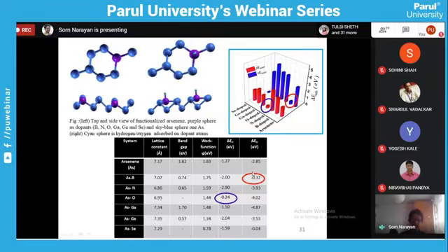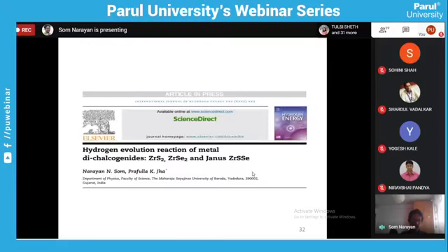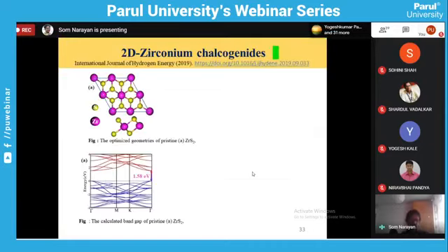And we now go to another system, that is zirconium Janus, ZrS2 or ZrSe2. We know that ZrSe2 is used as a photocatalyst in bulk also, but in the case of 2-dimensional, it also exhibits a band gap of 1.58, which is in the range of 1 to 2 eV, that can be used as a photocatalyst.